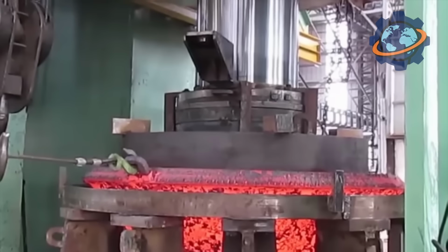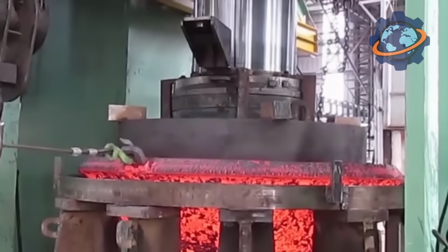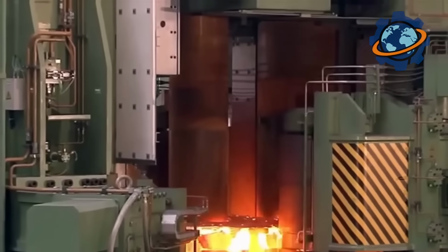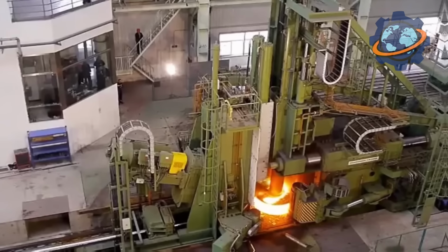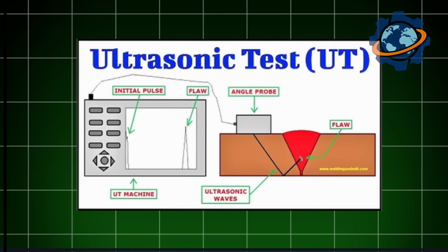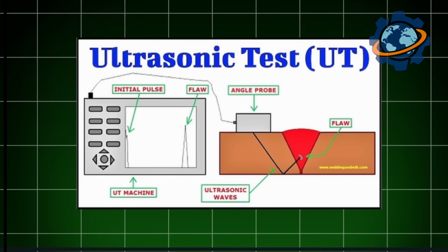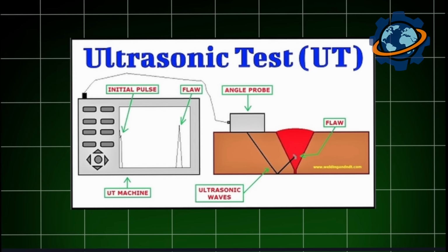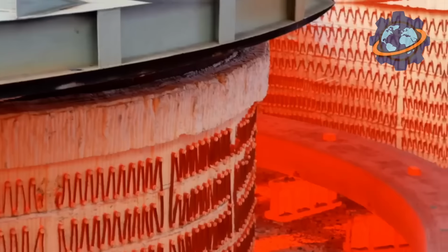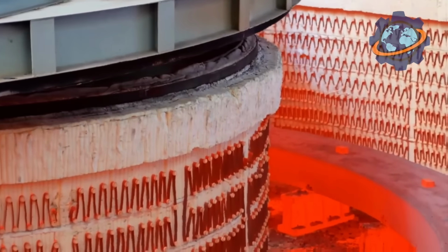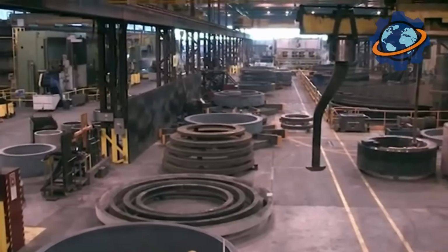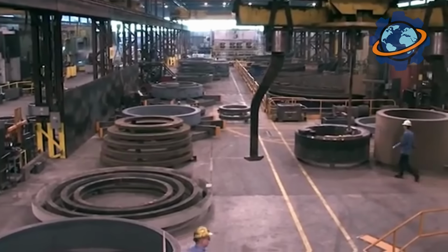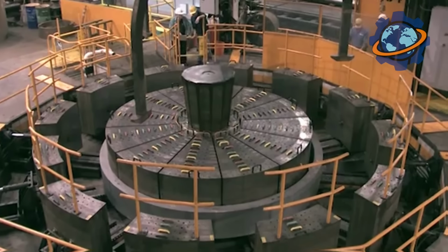The ring goes through heat treatment, heated and cooled on a precise schedule to lock in the steel's key properties: yield strength, impact toughness, resistance to creep at high temps. Then come the endless checks: ultrasonic testing for hidden flaws, mechanical tests on samples sliced from machining allowances, hardness measurements around the whole perimeter. Only when engineers are confident the metal behaves identically at every single point does the part get cleared for duty in a nuclear unit.